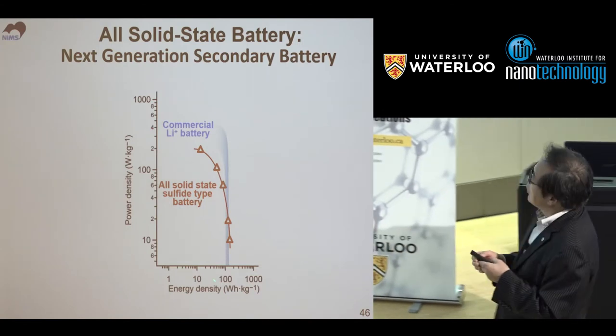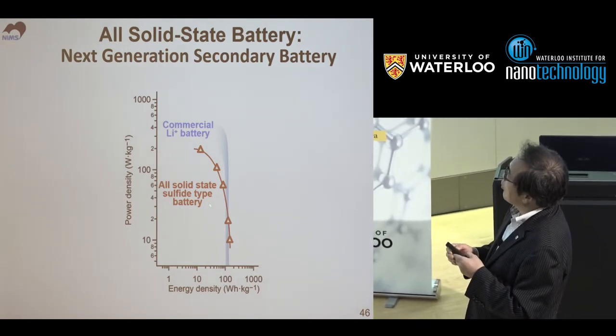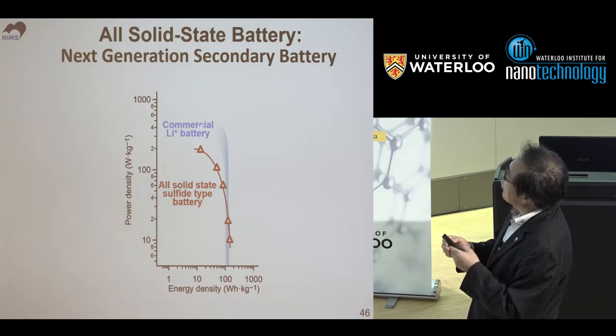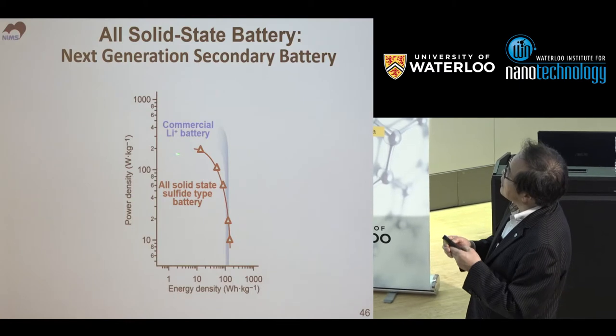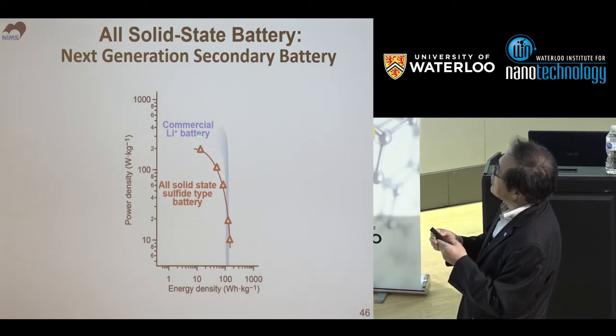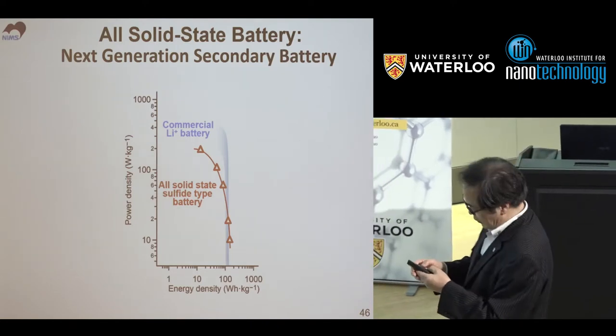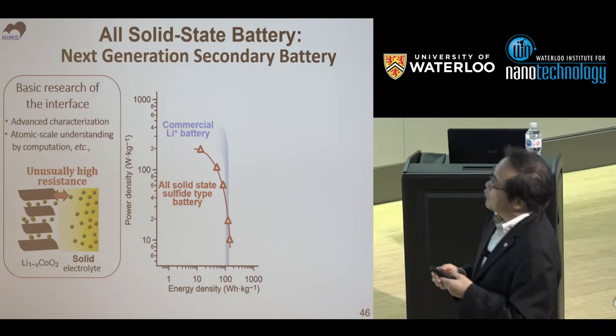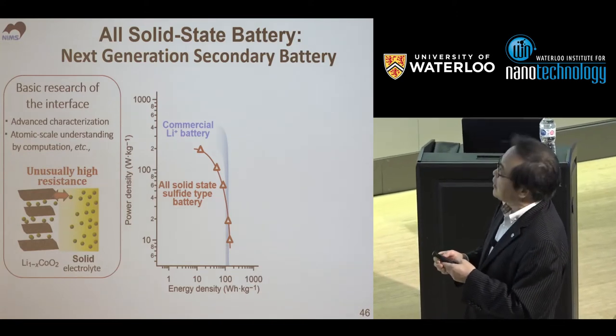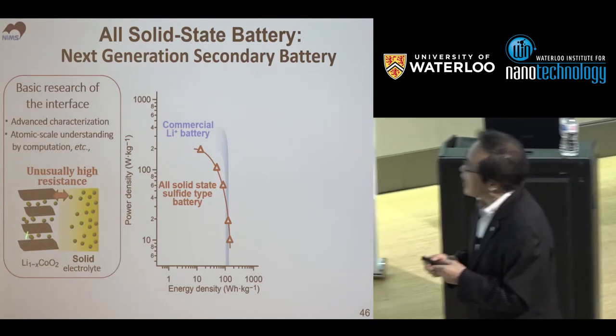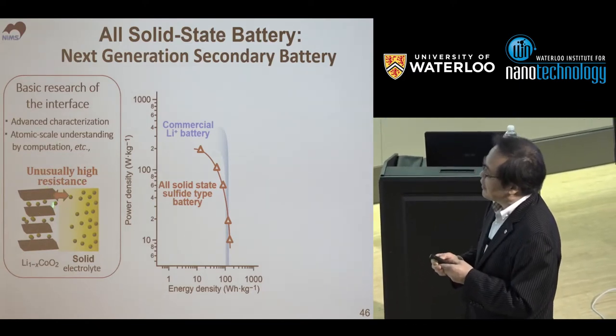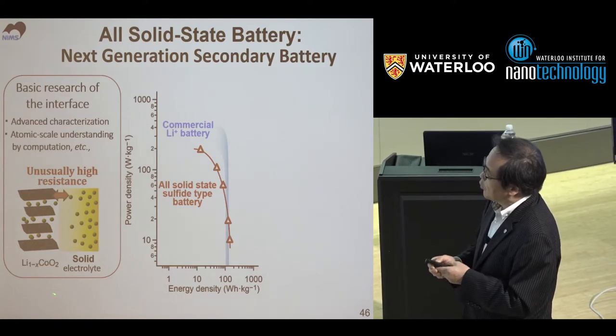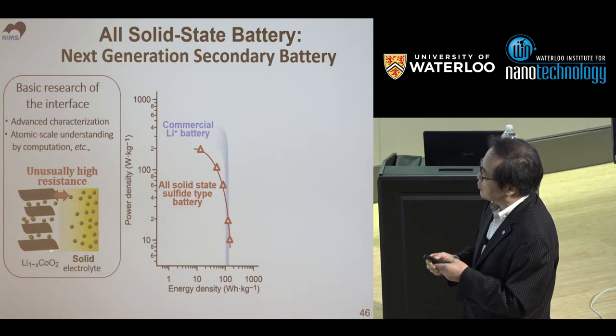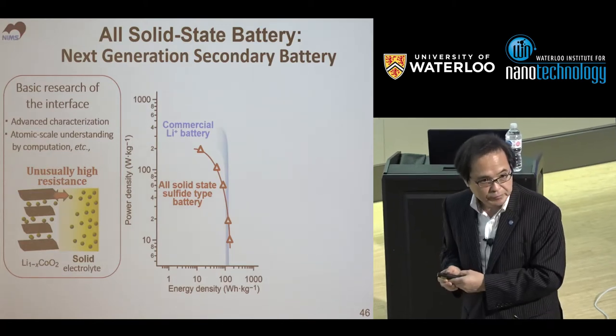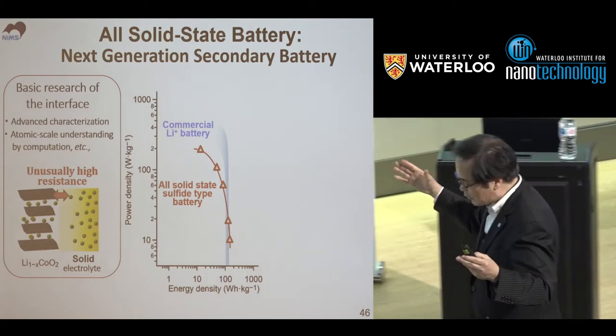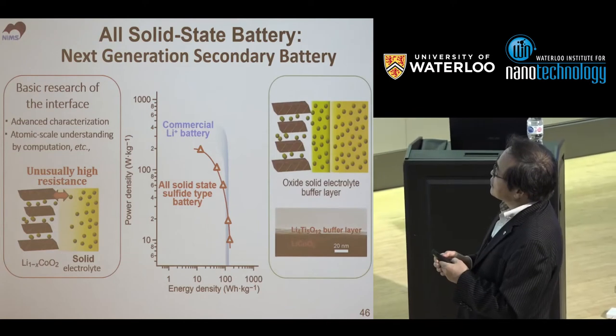However, although the energy density of the all solid state battery is equivalent to conventional commercial lithium batteries, the power density is much, much lower. This is a very big problem. We analyzed the reason with basic research methods, especially at the interface. Then we found that unusually high resistance exists between the lithium cobalt oxide electrode and the solid electrolyte interface.